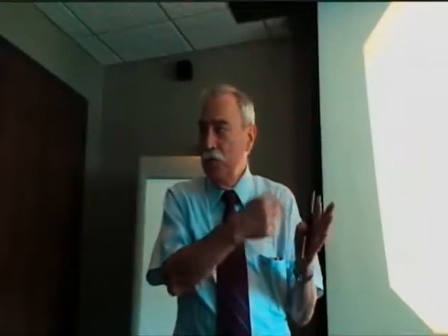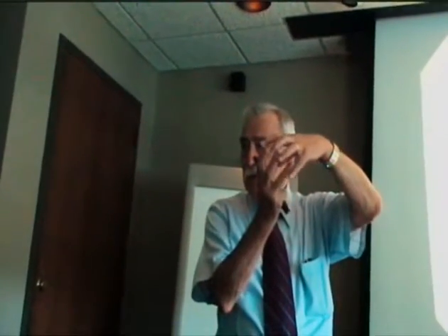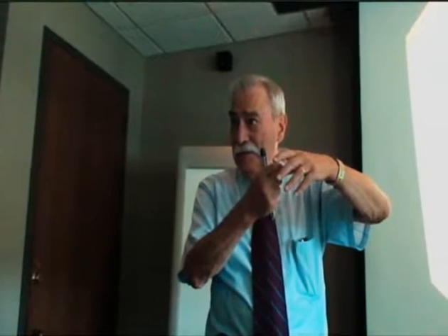Our NMR shows that the tin is probably 8 coordinate. Because we have a number of 6 coordinate tin compounds, and we measure the NMR, and it's around negative 600 to 700. And this stuff is always past negative 800. And that's in the regime where there are few 8 coordinate tin compounds we fished out of the literature. So if this tin is 8 coordinate, it's surrounded by oxygens. I don't think that this mild reaction is going to make the aldehyde or ketone touch the tin.